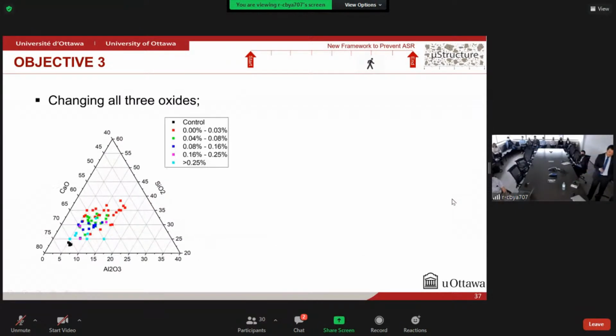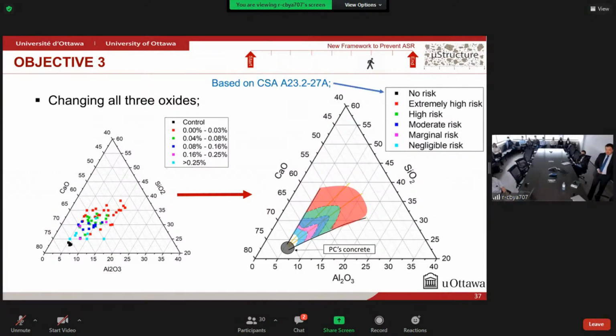With these results, and also summing with the results from the literature, we were then able to propose a framework to mitigate ASR in concrete, in which we have different regions, and each region here is based on the risk of ASR development, as in the CSA 27A. And for example, if we have extremely high risk of ASR development, the composition, the mixture of our binder materials and the chemical composition of them together should be within this red zone here to prevent the development of ASR, or above this zone, and so on for the other mixtures, for the other risks of development.